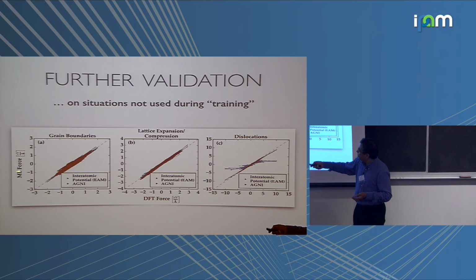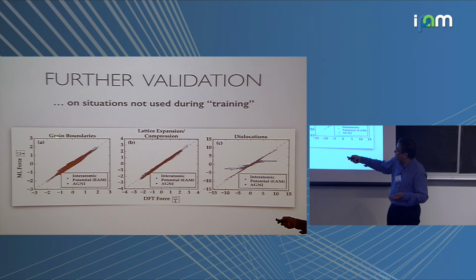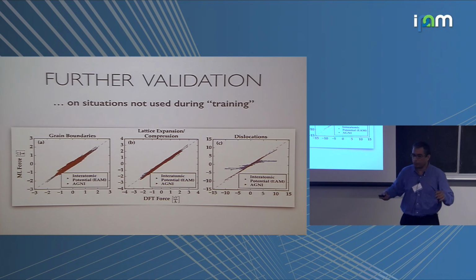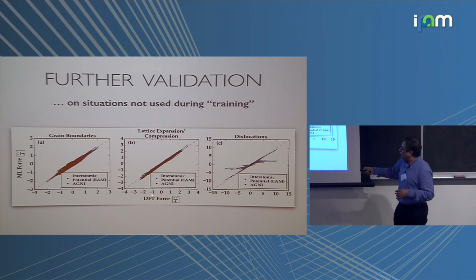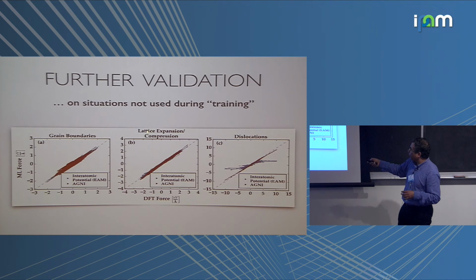So, machine learning force versus the DFT force for grain boundaries. Our force field, which we call AGNI, by the way, is all red. And then the interatomic potential based on the embedded atom method is very competitive. There's not much difference between the two. Here is the corresponding plot for expanded and compressed situations. Once again, both the methods are almost equivalent to density functional theory. But when you go to the edge, so